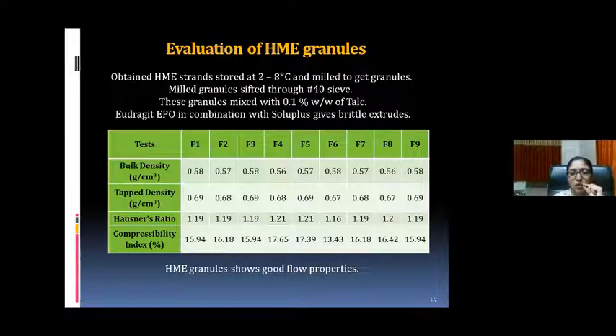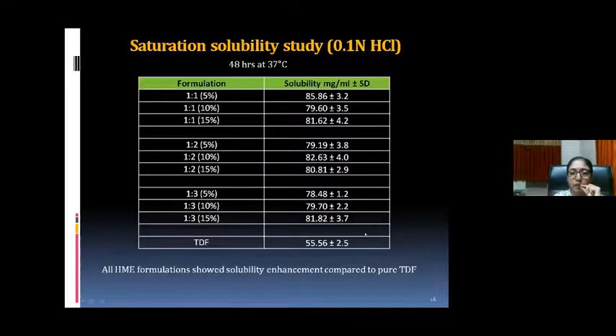These are the evaluation parameters that were carried out. The pre-formulation studies showed good flow properties. Solubility was carried out in 0.1 normal HCl, and all of the solubility results showed solubility enhancement as compared to the pure drug.